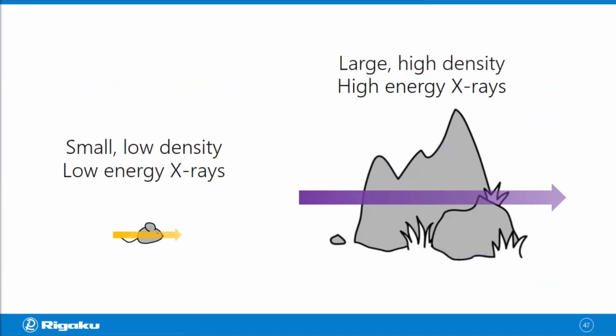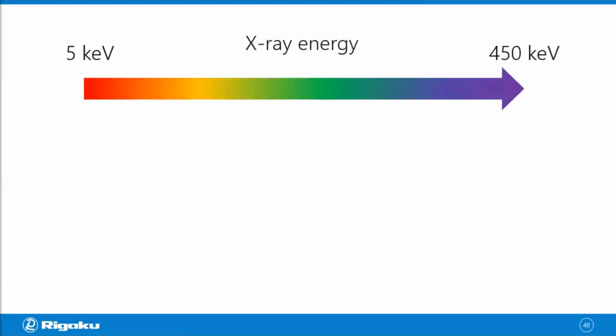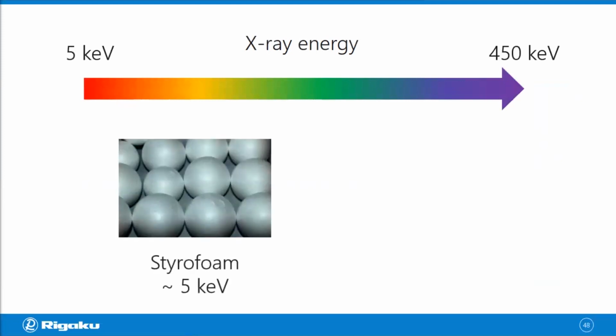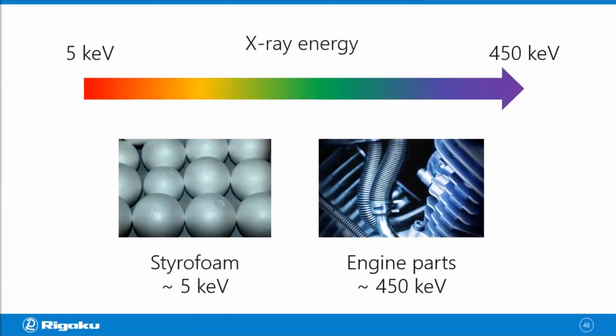Now for the range of X-rays you can use, for the commercially available X-ray sources, you can find different sources from 5 keV to about 450 keV. And that energy range translates into density. For example, styrofoam can be imaged with 5 keV X-rays. And if you want to look at something like engine parts made of stainless steel, then you want to go to 450 keV to see them. So that's, density wise, roughly the range you can look at with those X-rays.